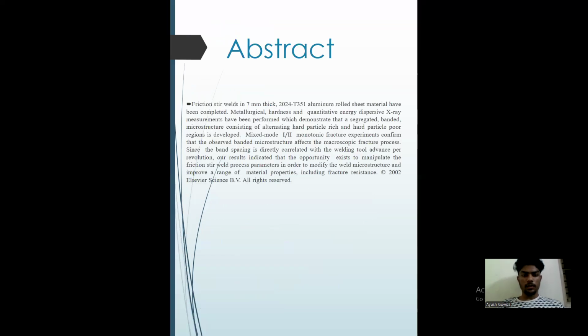Abstract. Friction stir welds in 7 mm thick 2024-T351 aluminum rolled sheet material have been completed. Metallurgical, hardness and quantitative energy dispersive X-ray measurements have been performed, which demonstrate that a segregated banded microstructure consisting of alternating hard particle-rich and hard particle-poor regions is developed. Mixed mode I-II monotonic fracture experiments confirm that the observed banded microstructure affects the macroscopic fracture process.